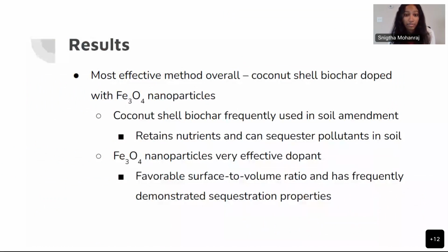And as stated in the beginning of this presentation, this was hypothesized. Coconut shell biochar is frequently used in soil amendment processes because it can retain nutrients and sequester pollutants in soil. These properties were expected to transfer over for water contamination, and that's why I hypothesized that it would be efficient for this as well. Iron oxide nanoparticles are also a very effective dopant, and as stated, they have a favorable surface to volume ratio, meaning that there's more area available to sequester the pollutants, and it's frequently demonstrated sequestration properties in water contamination before. For example, in my research developing the ferrosponge, the iron oxide nanoparticles were utilized to remove microplastics in oil, which led to the expectation that they would be efficient in this application as well.